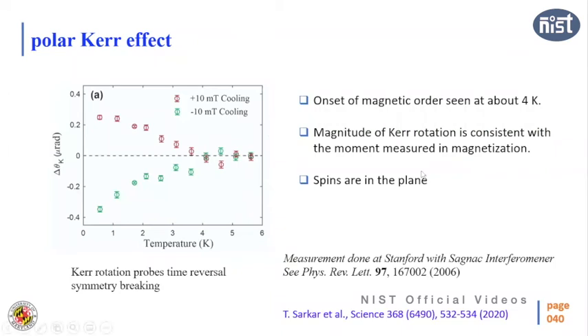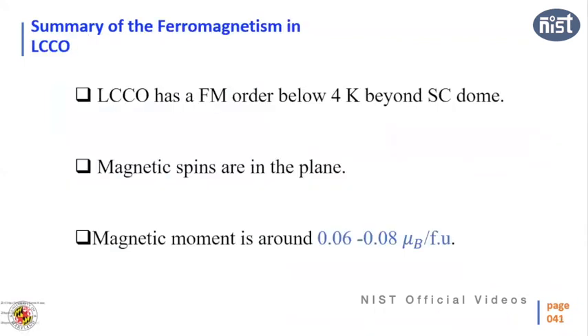And the magnitude of the magnetization measured using this technique also agrees with the value we found using our SQUID measurement. So what we found is that LCCO is a ferromagnet beyond the superconducting dome, and its magnetic spins are in the plane, and the magnetization we found is around 0.06 to 0.08 Bohr magneton per formula unit.